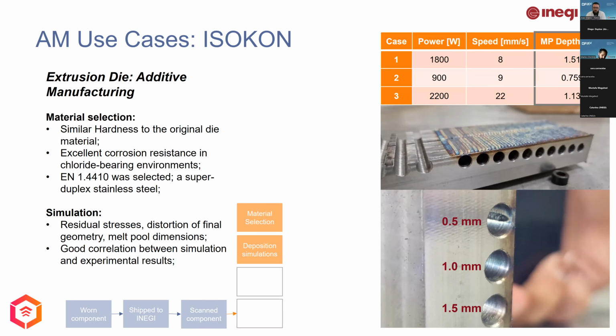The first hurdle was to find a suitable material. The chosen material needs to have a high surface hardness similar to the original material, and it should have excellent corrosion resistance to be able to withstand the extrusion process. Simulations to evaluate residual stresses and the distortions on the repair part were performed, as mentioned by Mustafa earlier, as well as simulations to understand the best parameters to use when the deposition occurs very near to the cooling channels internal to the die. After this, a set of experiments was performed to validate melt pool dimensions.